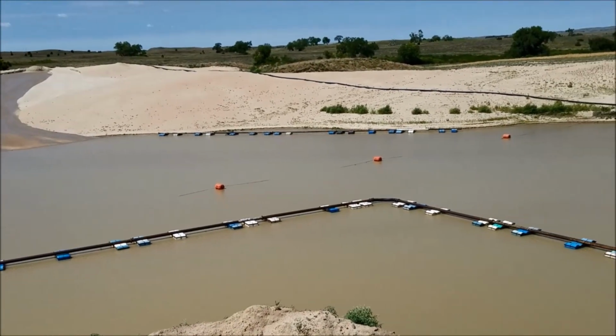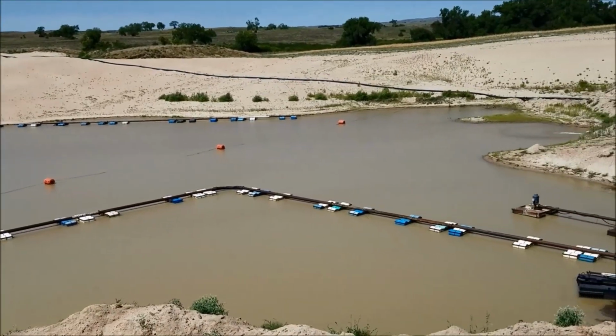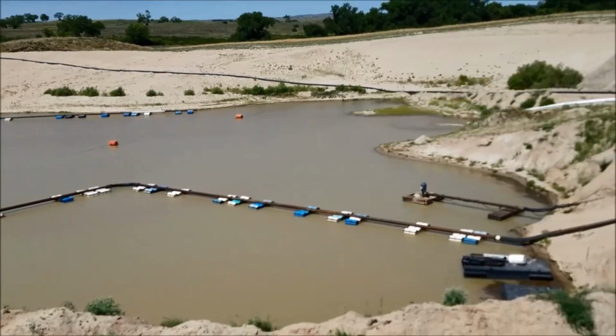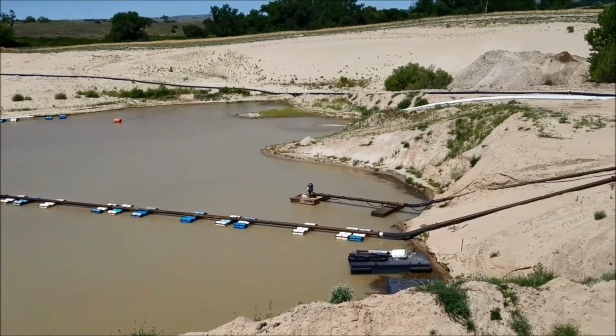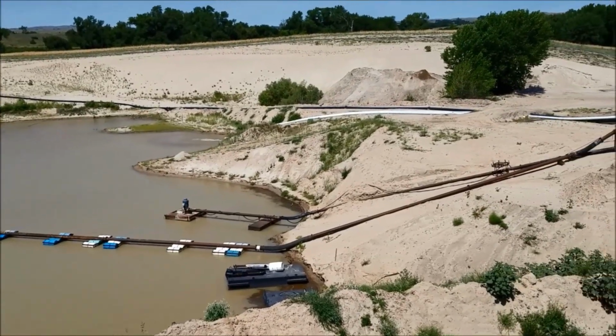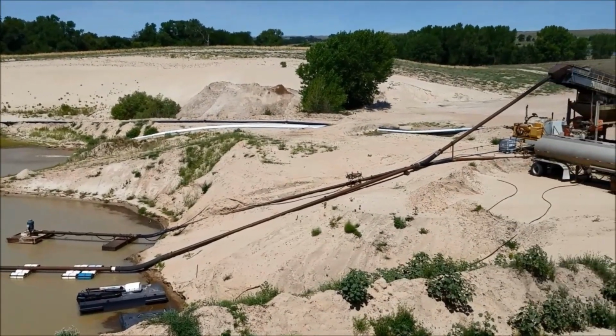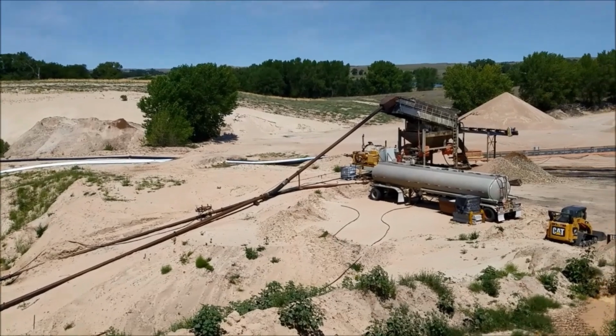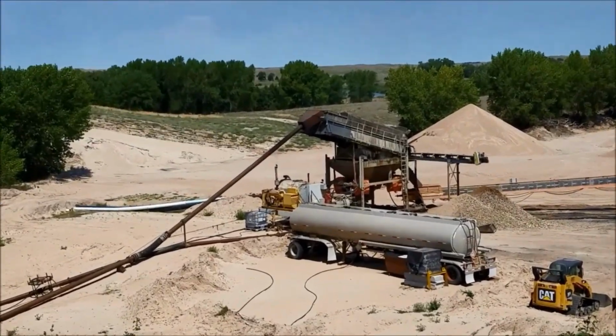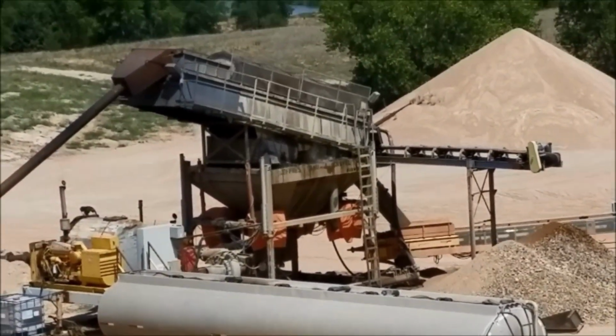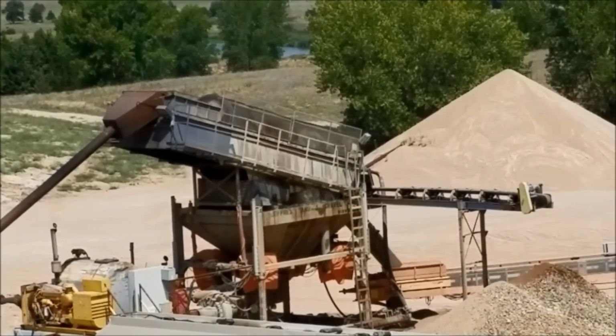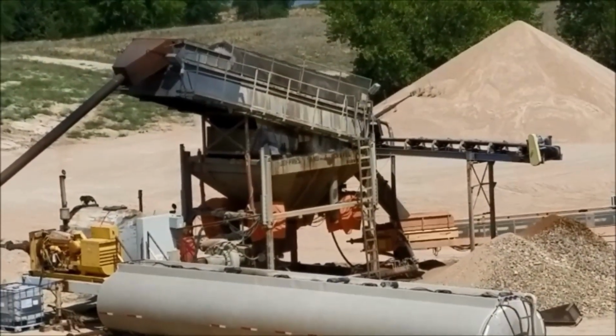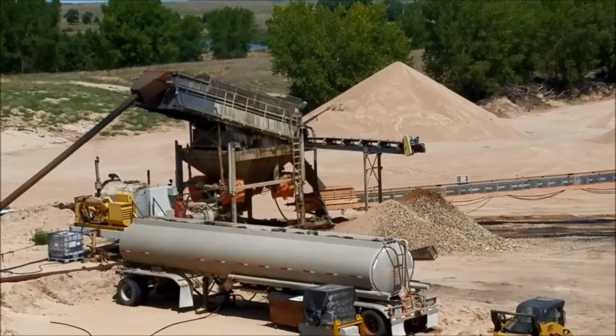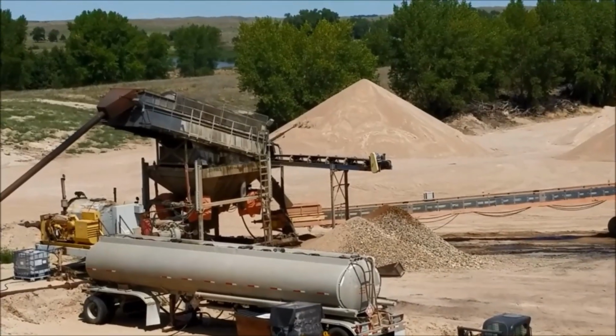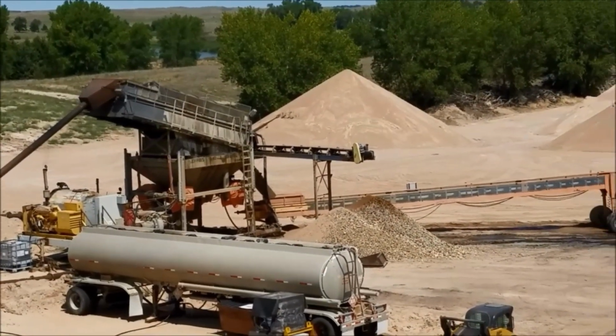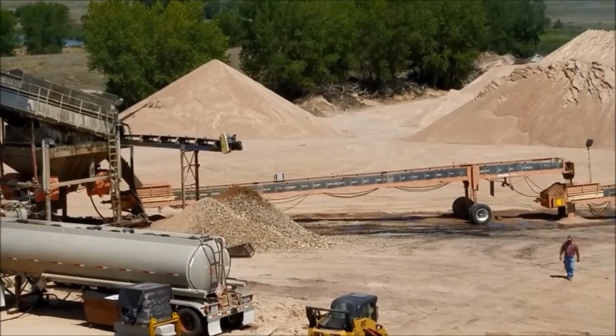It travels along this long pipe system until it gets to the screening plant. All of the aggregate enters the top of the plant and travels down the rotating drum. Inside of the drum, the aggregate runs through a series of sieves that separate it by size. Everything sand particle sized and finer is put to the side and kept. Anything larger is returned to a discharge pile.